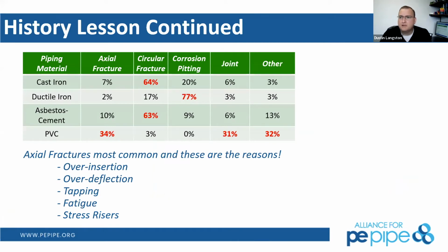So a little bit more on the history. Peter touched on this a little bit. Cast iron pipes, again, very good, a very thick walled product, but they were susceptible to overloading, causing circumferential cracks, fracturing. And these were catastrophic. They would be big breaks. And that was just usually from overloading. If you overloaded that pipe type, put a building on it, under a road, things like that, that would fail with a circular fracture.